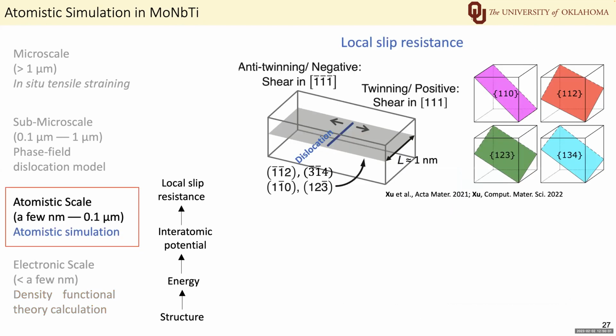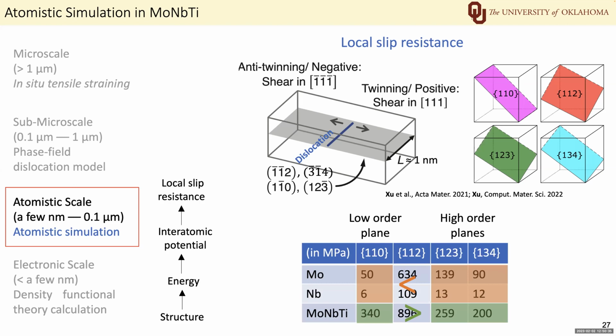So with the interatomic potential in hand, I conduct atomistic simulation at a higher length scale. I built a simulation cell that contains a short dislocation. The slip plane can be the 110, 112, 123, or 134 plane. I then calculate the local slip resistances of the dislocation. We find that in pure metals, the local slip resistances on the two higher order planes are higher than that on the low order 110 plane.